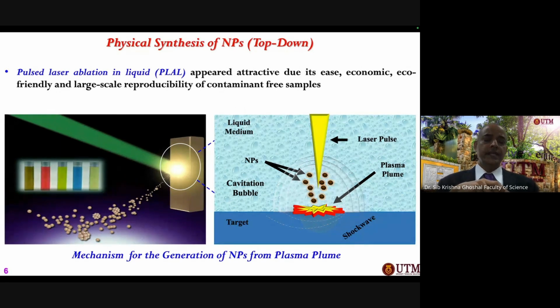So this is the key, and this is the catch of this game, that we can use the pulse laser ablation technique to make this kind of pure, highly nanocrystalline, highly spherical nanoparticles using pulse laser ablation in liquid, where optical and electronic densities of states can be manipulated in a wide way.